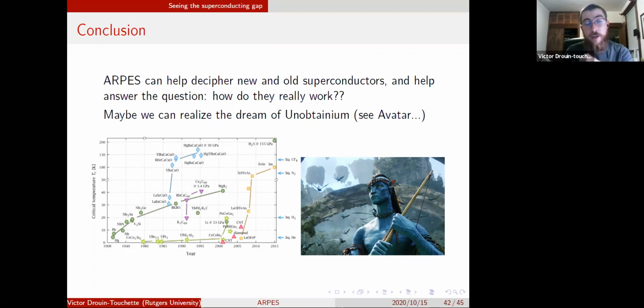And what's fascinating is that those materials that are being shown right now to have high temperature, room temperature superconductivity are actually BCS superconductors, electron phonon superconductors. And the reason they're such high temperature superconductors is because they've been engineered with such a high pressure that the phonons are extremely strong. They're among the strongest you could ever have. So the electron phonon coupling is extremely large, so there's a high critical temperature. So it's kind of a feat of engineering. People predicted these hydrides a while back, and lo and behold, they were found a couple of years ago, and now they go all the way to 15 Celsius.